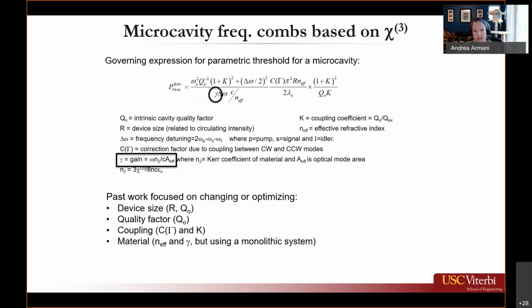And one way researchers are doing this is to make a device that has a really, really high Q factor, and solve a dispersion problem in order to get a lot of comb lines. We decided, after looking at this equation, that we were more interested in addressing this little gamma term in the bottom, which is actually the gain. So if we can maintain the quality factor, or at least keep it stable, yet address this gain term, then we could get similar performance. So basically change it from being an integrated device problem to being a material science problem.